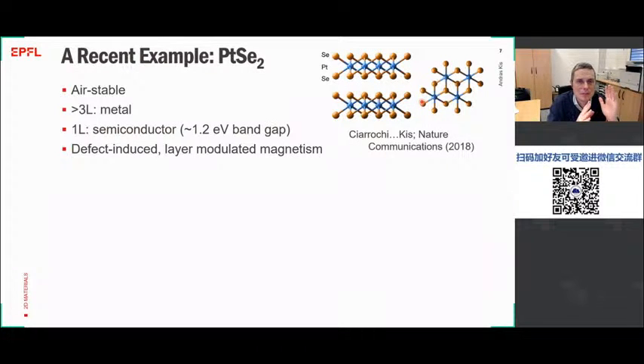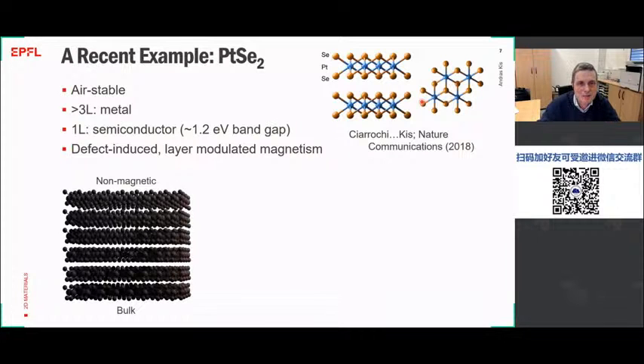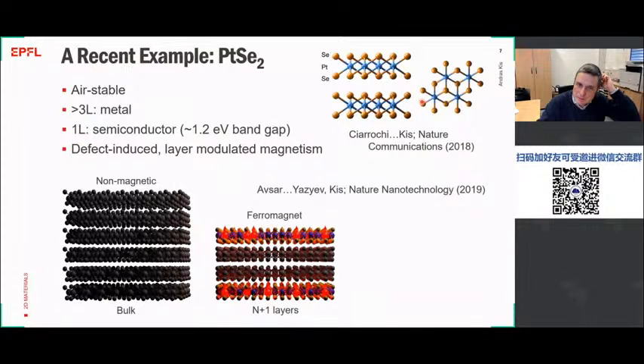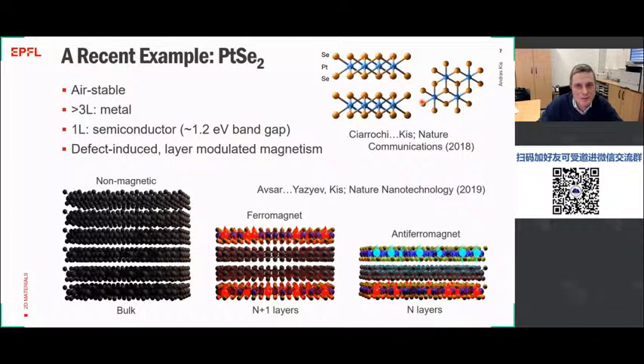But in parallel with this tunability from a single layer semiconductor to a bulk metal, you can also induce magnetism in this material. The bulk material is non-magnetic, but with the thickness lower than 10 nanometers, whenever you change the thickness by one layer, you can switch the magnetic behavior from antiferromagnetic to ferromagnetic. And the single layer was recently shown to be an antiferromagnet. So this magnetic tunability goes in parallel with the electrical tunability, and it makes this material very rich in different types of properties. Many other 2D materials are like that. They can change their behavior radically by just changing the number of layers in small thin crystals.